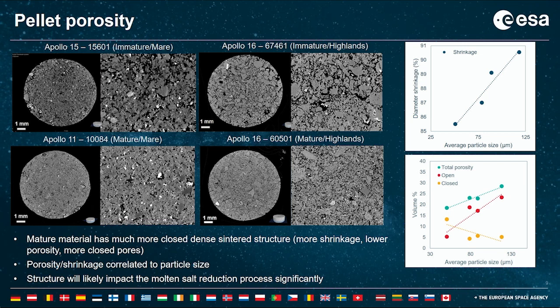And this is reflected in the data that we can see, where the shrinkage is correlated to the average particle size and also the total porosity. So overall, we find that the mature material has a much more closed and dense structure, more shrinkage, lower porosity, more closed pores. And the porosity and shrinkage can be correlated to that particle size.